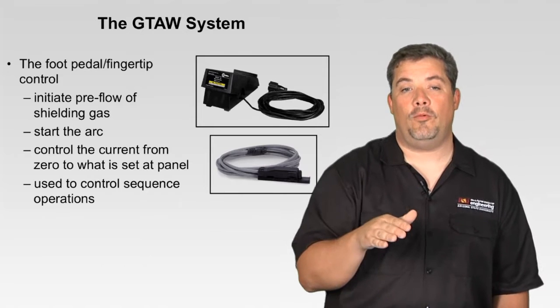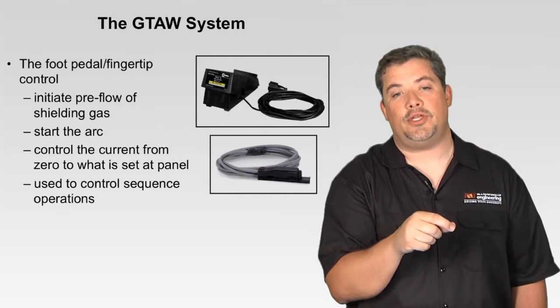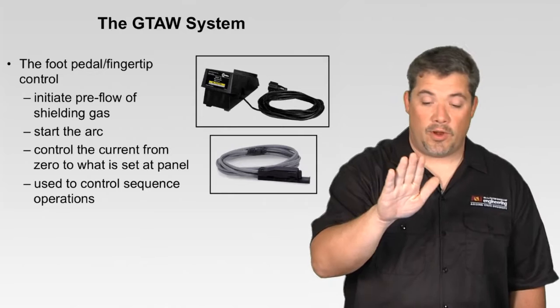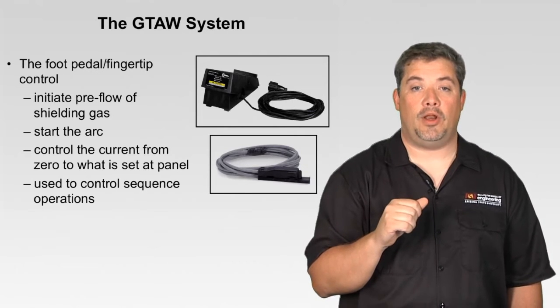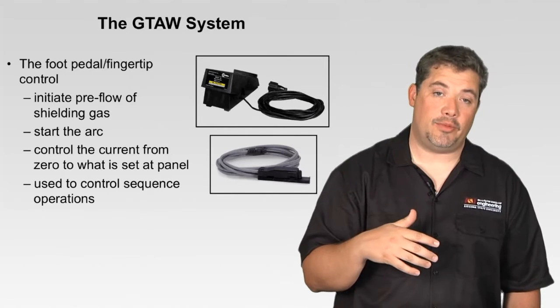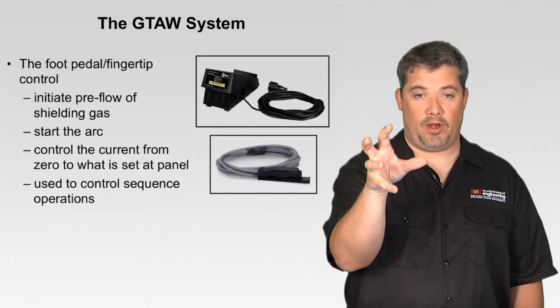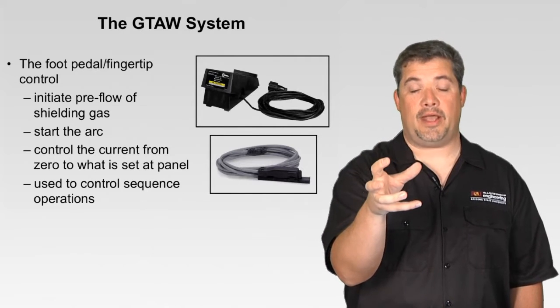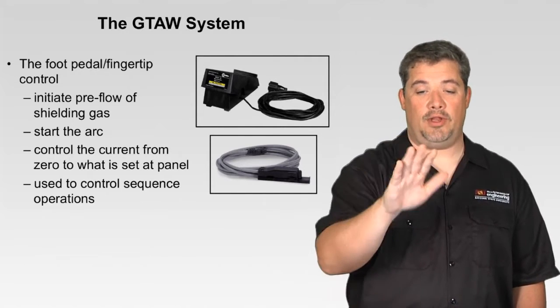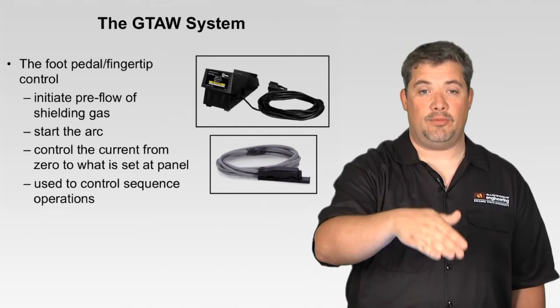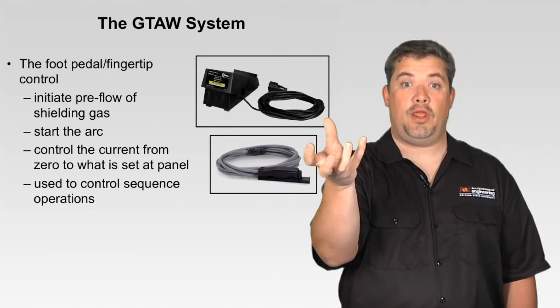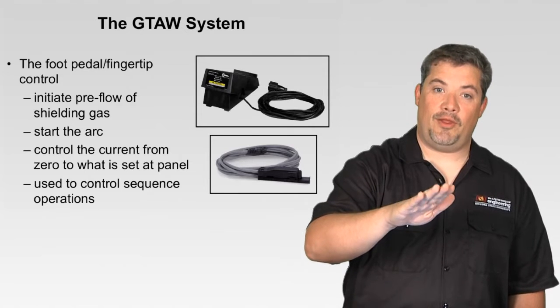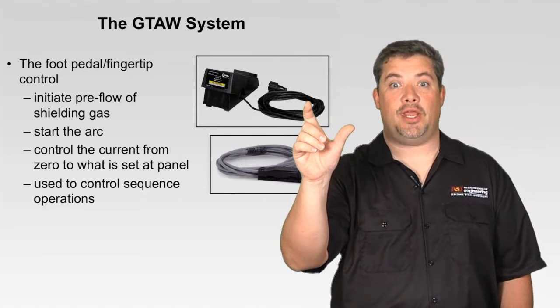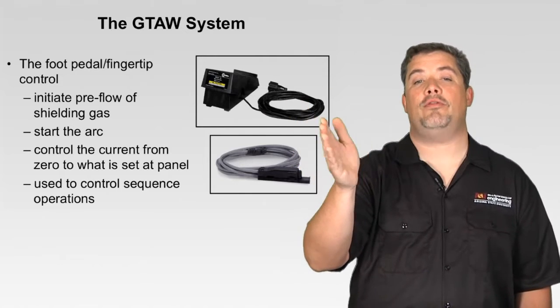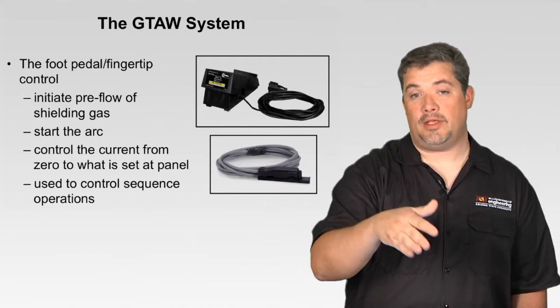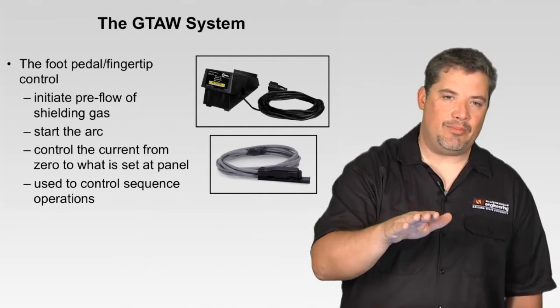And the way that the foot pedal works is if I set the panel of my machine at 100 amps, when I floor that foot pedal, I get 100 amps. I might have a 300 amp machine, but I'm limited by what I've told the dial on the machine to max out at. So if it's at 100, I've got a pretty good 0 to 100 range in my foot pedal. If I go to 300, that slight move on my foot pedal is now a lot more amperage change. So you want to get that down to around the zone that you need to maximize your operating at, and maybe that 80% level is good.